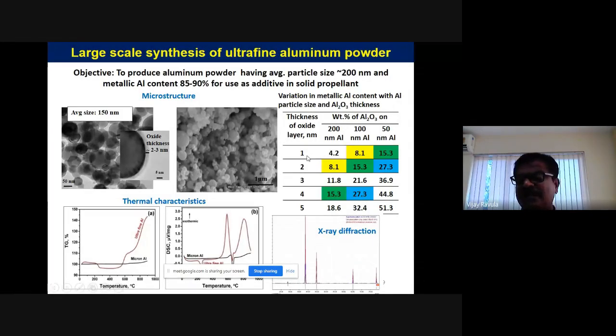Our group has done a lot of experiments on the thickness of the oxide. When you increase the thickness, obviously the alumina, Al2O3, content also increases. But then that loses the heat generating capability of the material, right? So the enthalpy comes down. In order to have a balance, they tried different sizes, and you can see that as the size comes down, because of more surface area, there is more alumina, even going up to 15 weight percent with the 1 nm thickness.